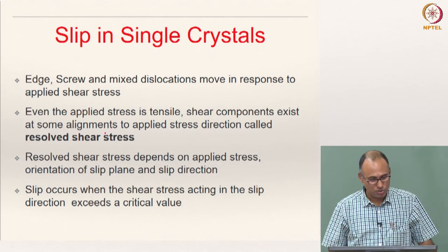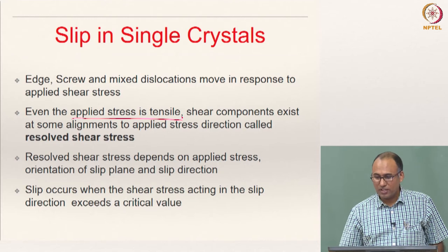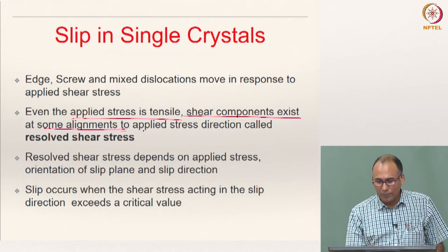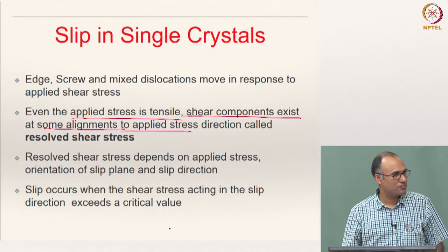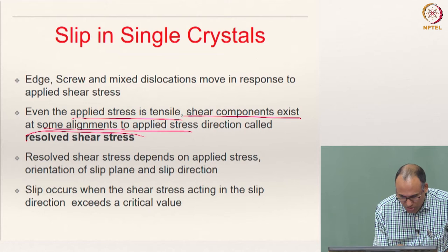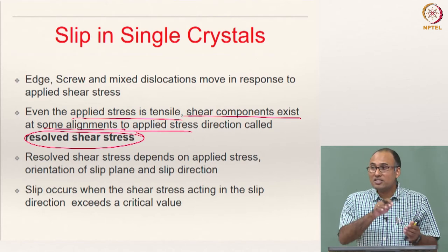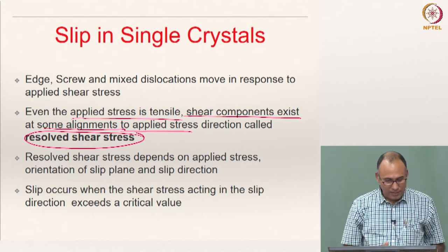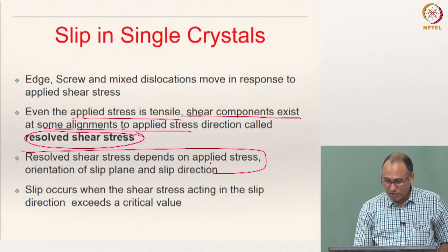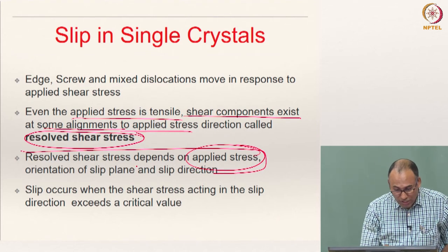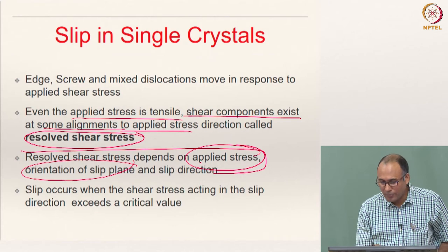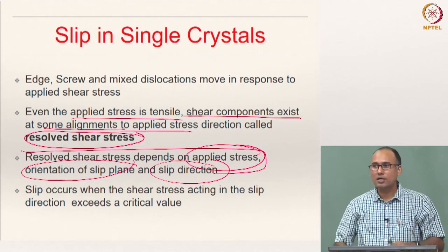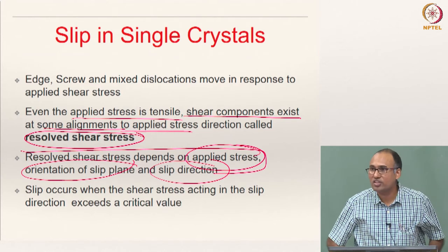The same applies here too. Even when the applied stress is tensile, shear components exist at some orientations relative to the applied stress direction. That shear stress is called the resolved shear stress, and slip happens due to that resolved shear stress. The resolved shear stress depends on the applied stress and the orientation of the slip plane and slip direction to the applied loading.